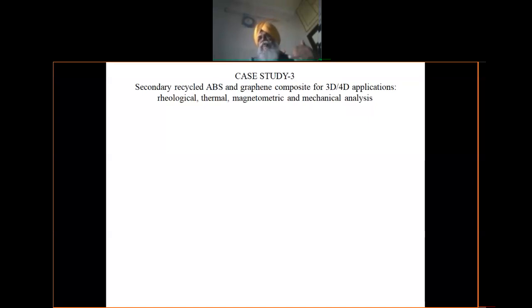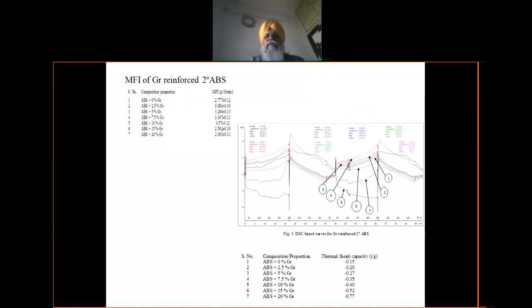But in our country, most of the work is in the primary and the secondary recycling, right? So this is more clear from here now. So what we did is we put some graphene in the secondary recycled ABS. Let us say initially 0% by weight graphene, then 2.5%. Then in different weight proportions, we are going to add different quantities of the graphene into it. And what we observed is the different MFI, right? So as the MFI is increasing, basically I can have availability of a thinner section. As the MFI was decreasing, I cannot have a thin section preparation with me, right?